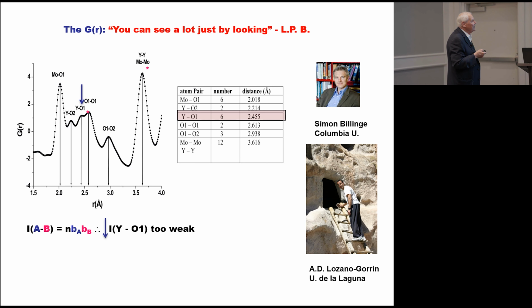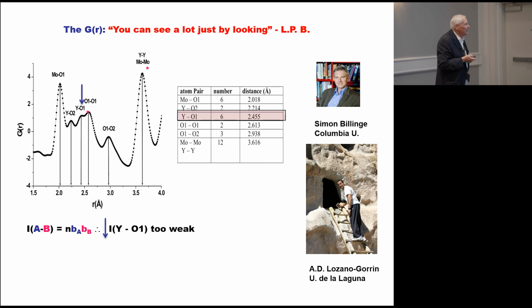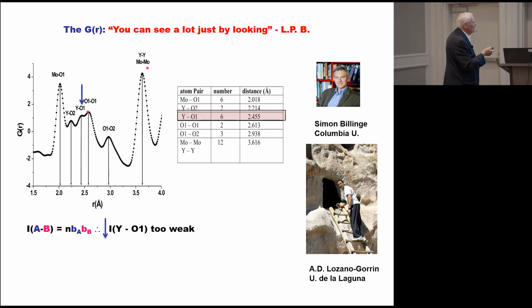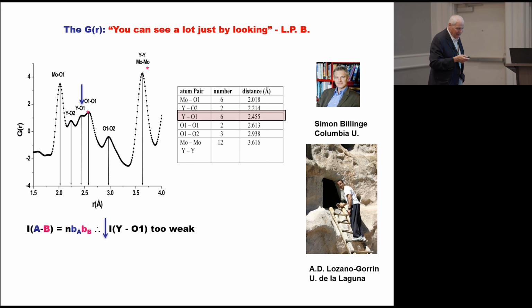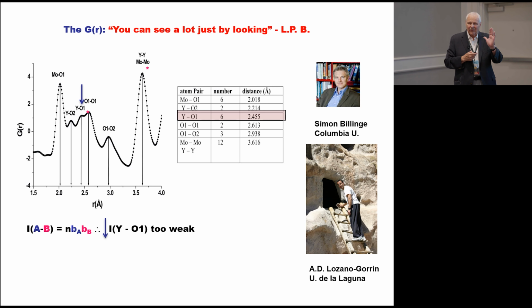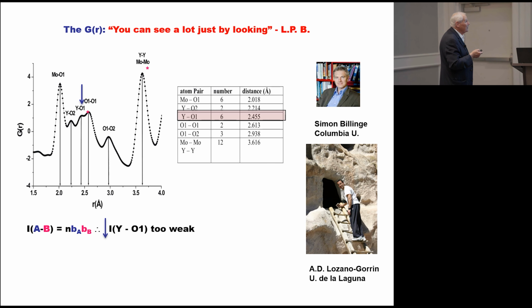All right, so my next comment is that I will quote Yogi Berra again, by paraphrasing: you can see a lot just by looking at the diagram. So this is the raw G(r), and I focus your attention on the yttrium-oxygen 1 peak. It has 6 neighbors, and so its intensity in the G(r) should be almost the same as the intensity in the molybdenum-oxygen peak, which also has 6 neighbors. By the way, the scattering lengths of yttrium, oxygen, and molybdenum are all pretty much the same. That's another feature of neutrons. So it's clearly a sign of disorder. It's very weird. It shows up very simply in this peak.